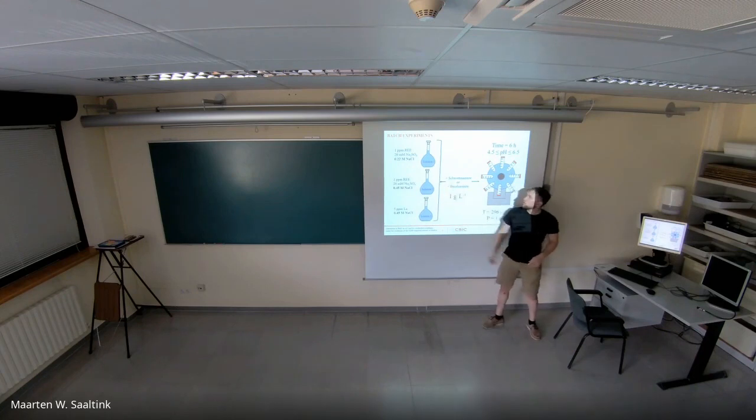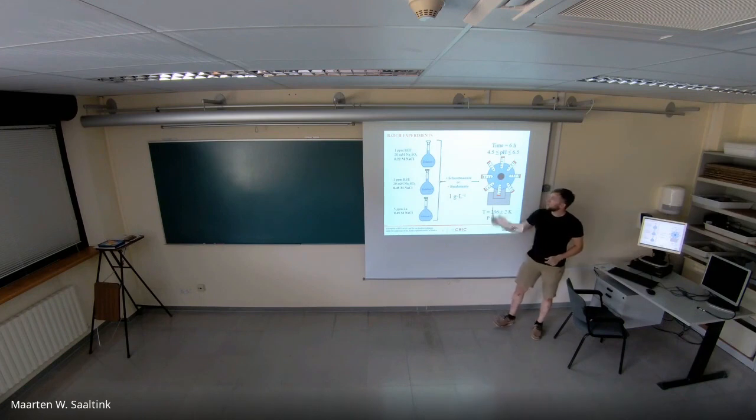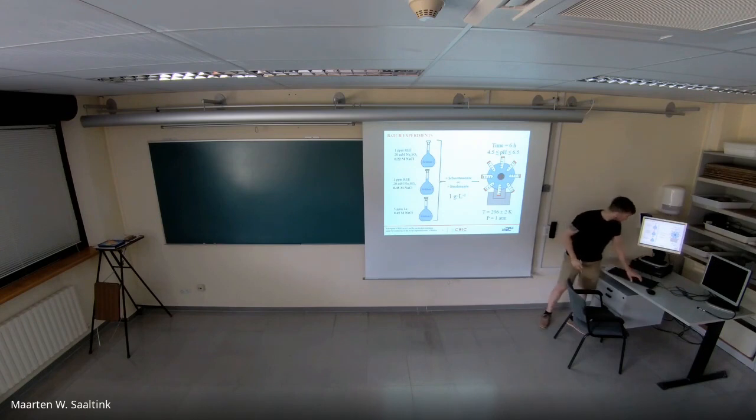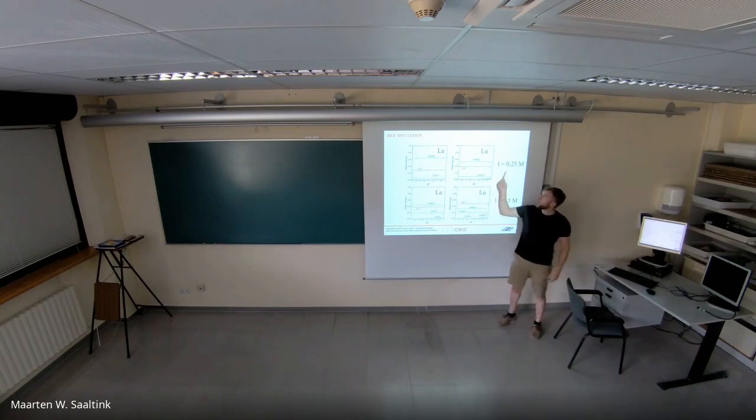These two solutions were mixed with schwertmannite or basaluminite with a solid-liquid ratio of 1 gram per liter, and then they were shaken for 6 hours at different pH depending on the liquid, and at standard conditions regarding temperature and pressure. So this is the speciation of solution 1 and solution 2.